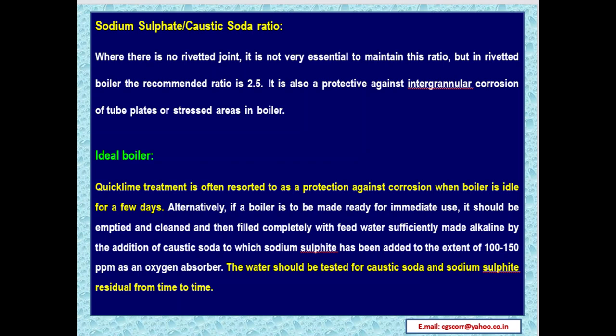Sodium sulphate and caustic soda ratio. Where there is no riveted joint, it is not very essential to maintain this ratio. But in a riveted boiler, the recommended ratio is 2.5. It is also a protection against intergranular corrosion of tube plates or stressed areas in the boiler.